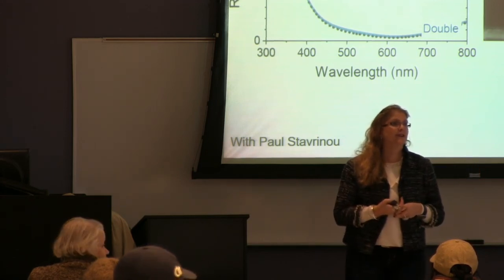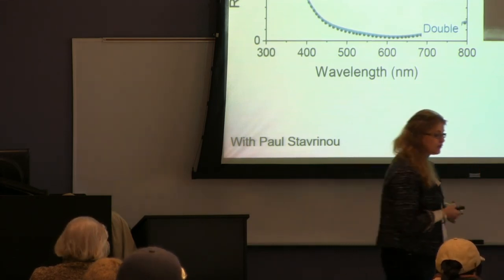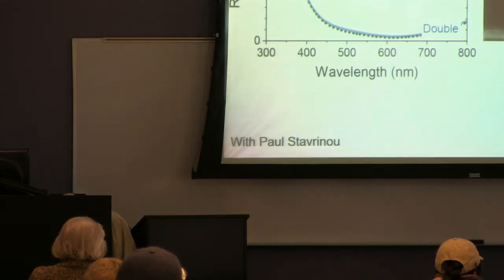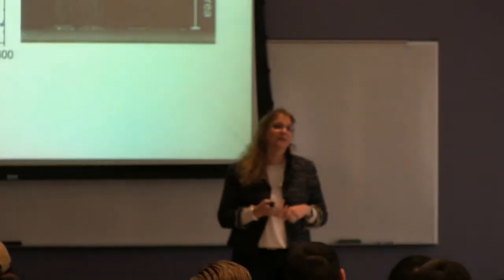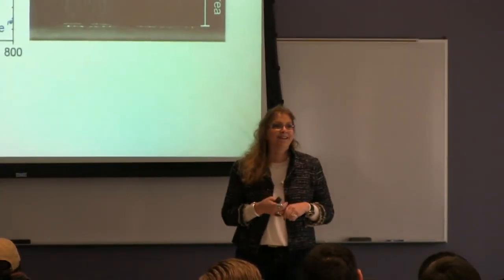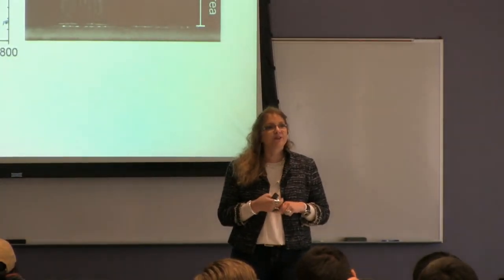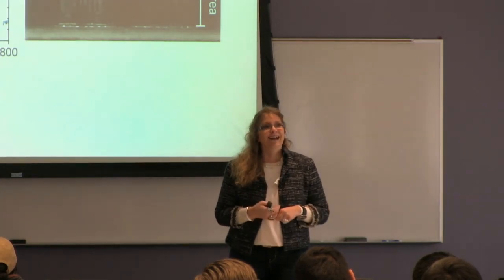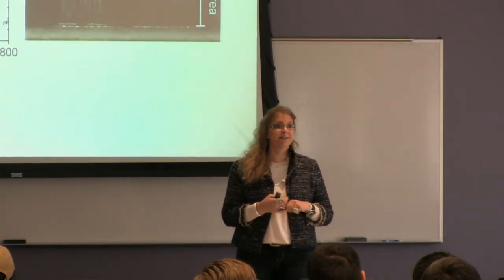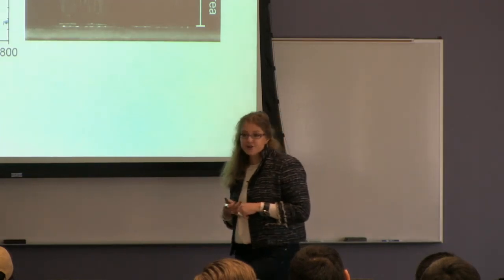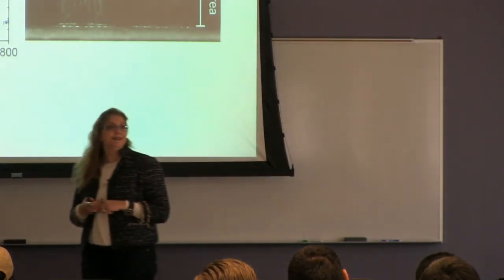And how do you control the thickness? The thickness we can control with the viscosity, so that's why PVA is so nice. We can get all the molecular weights and the dipping speed. And it's remarkably reproducible, because we can reproduce the mirrors. I was actually skeptical, but the mirrors show that it's superbly reproducible.